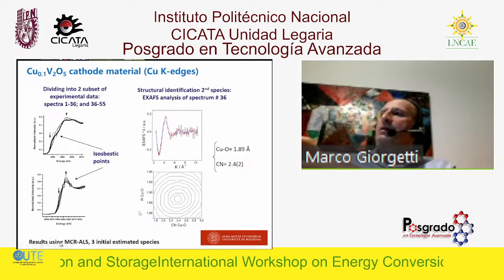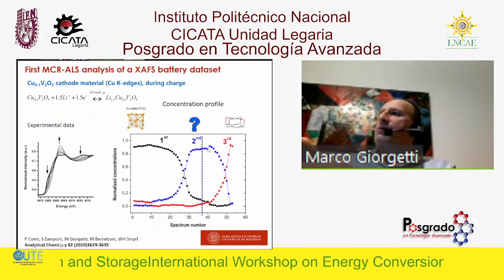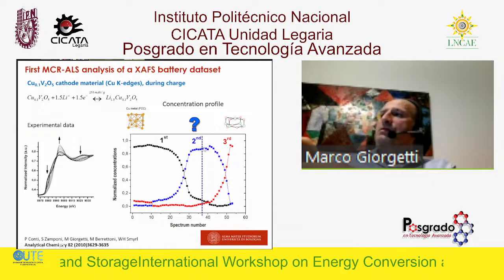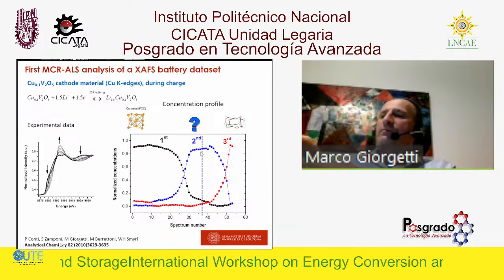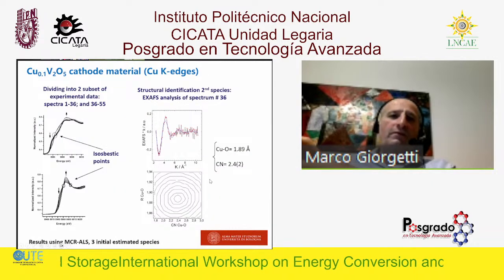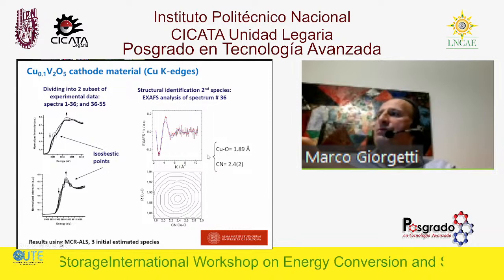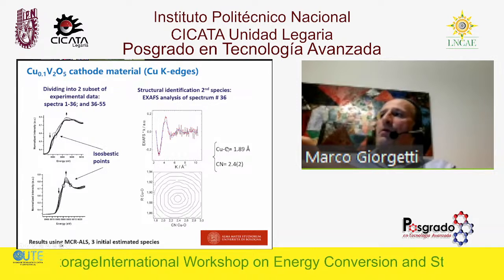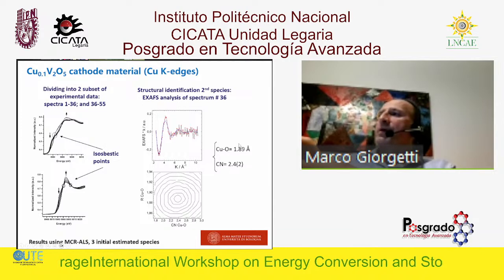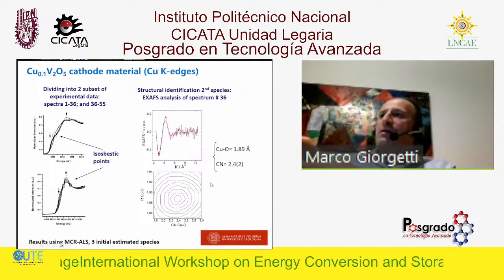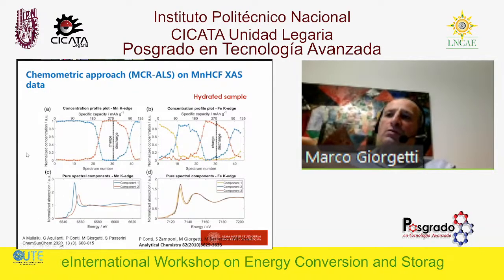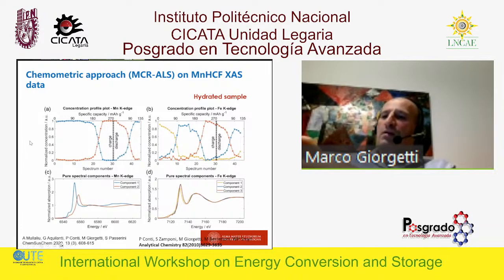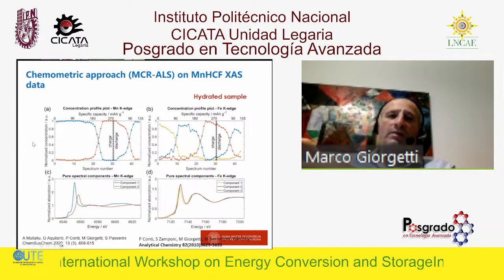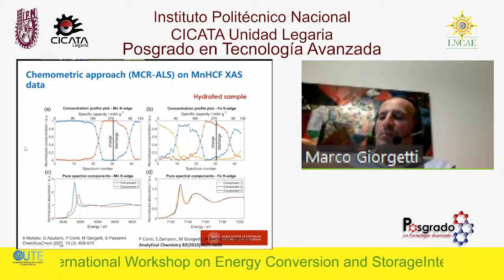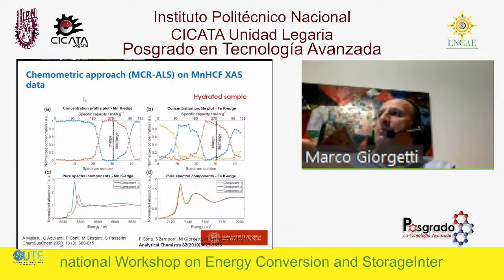Then, if you fit this spectrum and analyze it from the EXAFS viewpoint, you end up with a very precise figure for the copper-oxygen distance. This is what we have: the copper-oxygen distance is 1.89, and this is the coordination number. But now, what we do is kind of standard for us: when you have some operando XAS data, we use this chemometric approach.